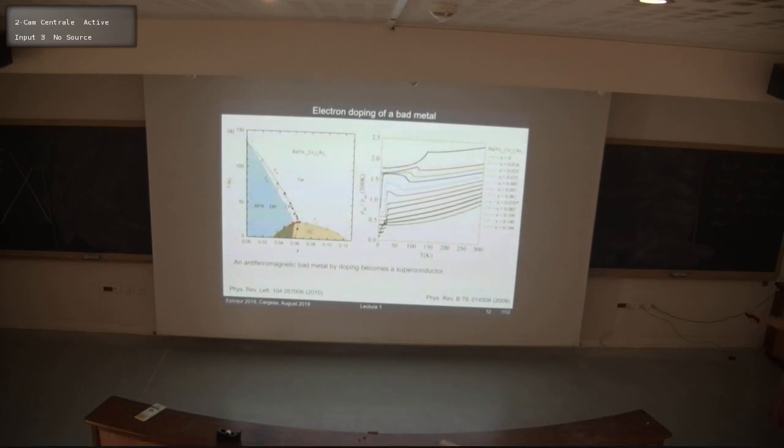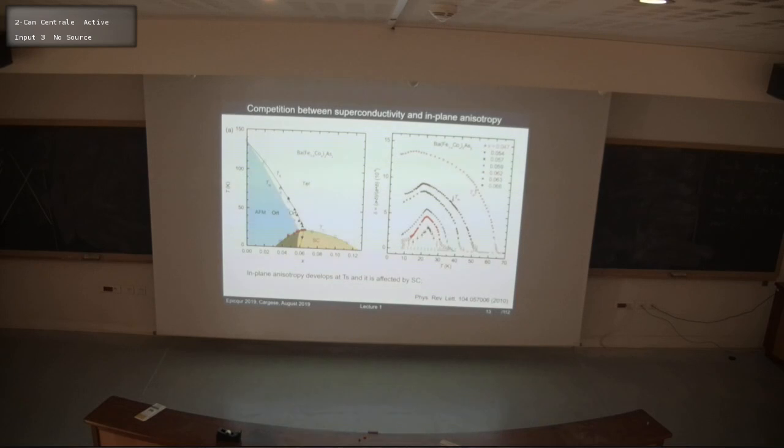Well, it's a transition. So the question is what type of transition it is. When we start in this phase diagram, we have a transition here, and that's the point of transition. However, as you introduce doping, you notice that these two curves actually disperse. So in reality, if you do a derivative of these curves, they are 2 features, and you need other probes to identify that. And here is another probe to identify the transition at high temperature, and these are structural measurements.